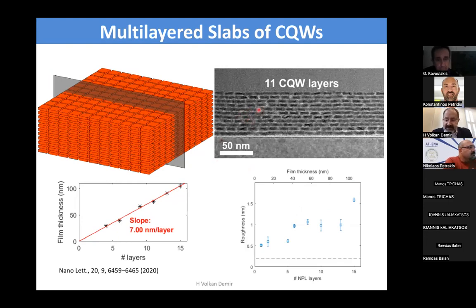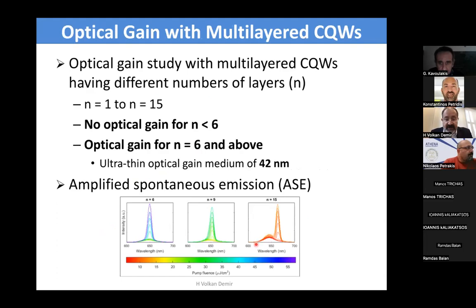This is just a demonstration for 11 monolayers. Going up to 15 monolayers, the increase in the film thickness is linear as expected. We did not observe up to this point any significant outlier, and roughness still stays within a few nanometers range as it should be. And this roughness is particularly critical because if we have a very rough surface, it means we will have strong scattering to outer half space, and observing amplified spontaneous emission will be very difficult.